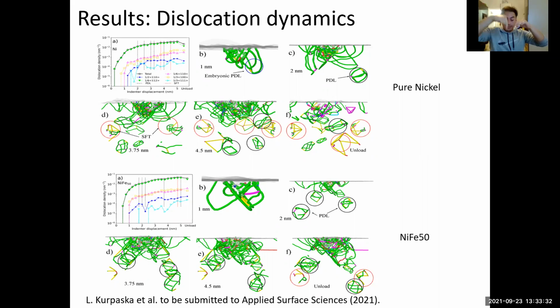So then inside you are creating interstitials, and these cumulative interstitials or linear interstitials, they are going to have some orientation according to the Burgers vectors that they have, and also you are creating vacancies. So all these processes that you are creating when you are pushing with this indenter, the result is the dislocations, nucleated and propagated. So when you are going deeper, the dislocations are propagating, as you can see here.